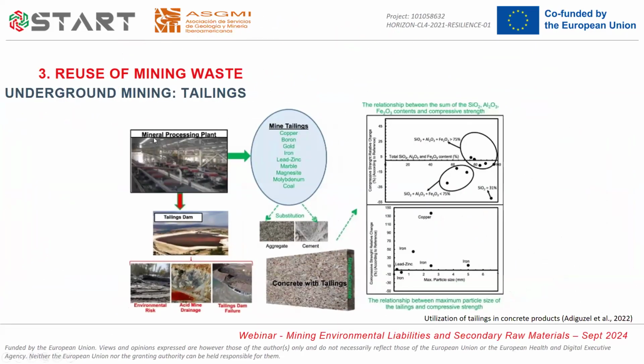Here there's an example of the use of these tailings in concrete. So from different tailings of different mines, from copper, boron, gold, we obtain the coarse size, the aggregate, that we can partially replace the sand of our concrete. And also from the slime, we can replace part of the cement used in this concrete. And here there are some relations between the composition of the tailings with the compressive strength, with the resistance of the concrete.